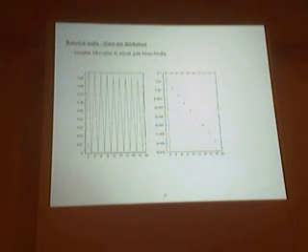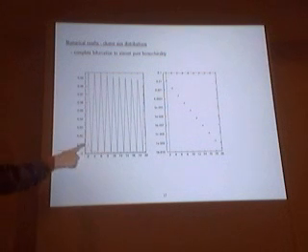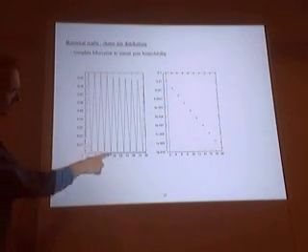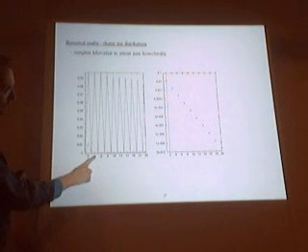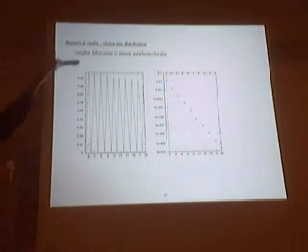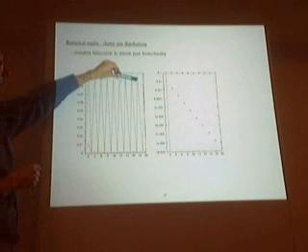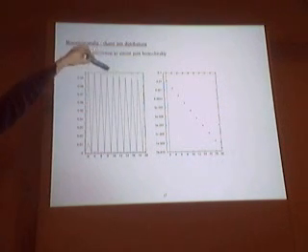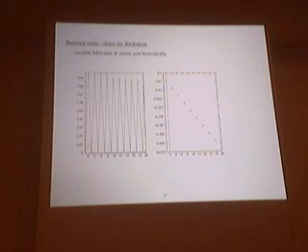So we seem to get quite encouraging results for those. And this chiral, this sort of complete bifurcation to one where you get pure homochirality, this is the size distribution for the one that's lost. It decays very quickly, you've just got a few dimers and hardly any tetramers. The size distribution for the one that's won decays very slowly, so you're getting very, very large clusters, almost flat. So you're getting a sort of equal distribution, a very broad spread distribution of sizes.